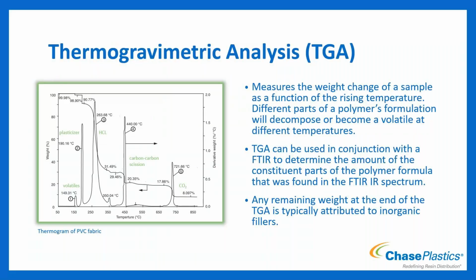So TGA is going to be a measure of change in the sample. It's weight change based on rising temperature. So different parts within the polymer's formulation are going to decompose or become volatile, give off at different temperatures. So we start at room temperature, lower temperature, and we raise the temperature up. And as it's being raised, different parts of it are going to burn off or decompose, and it keeps track of those changes in weights as it's going.